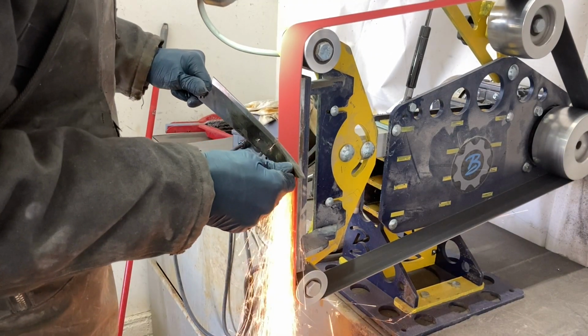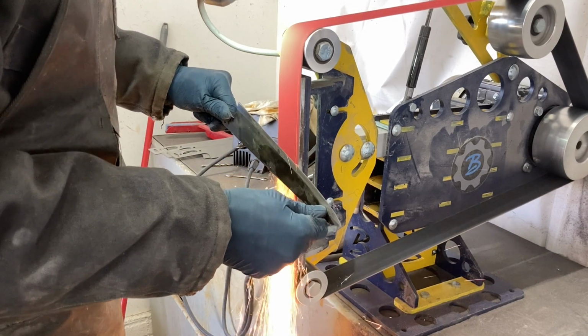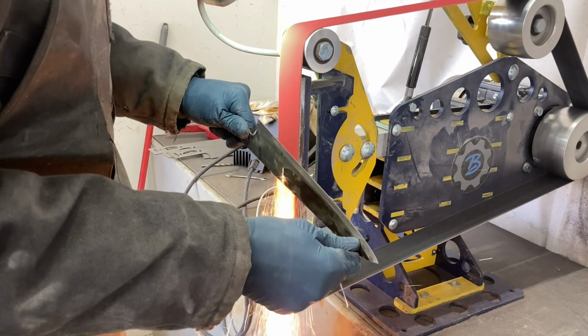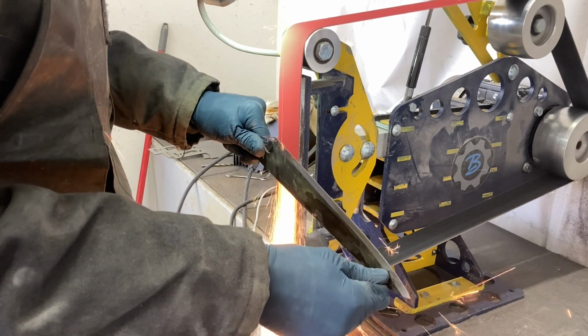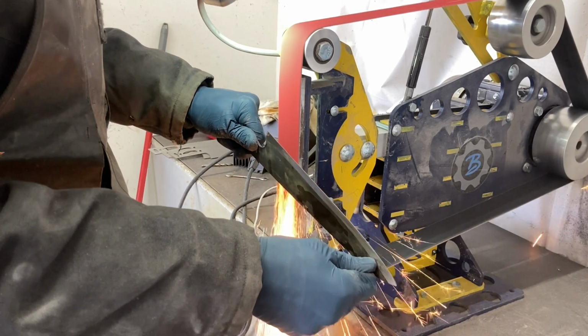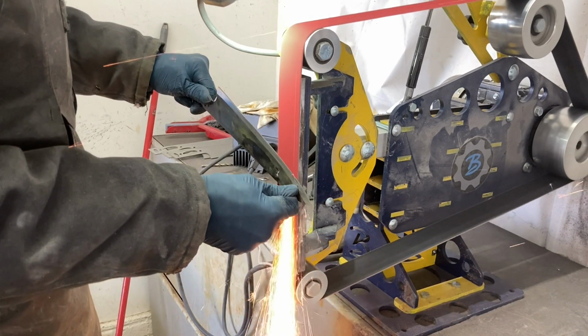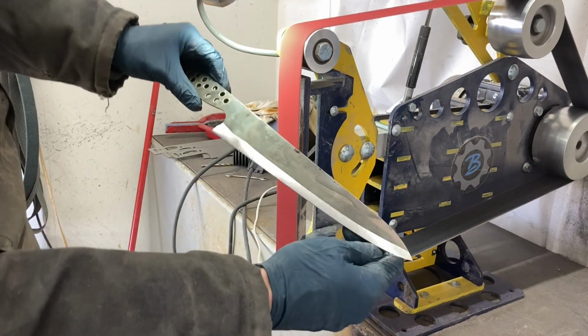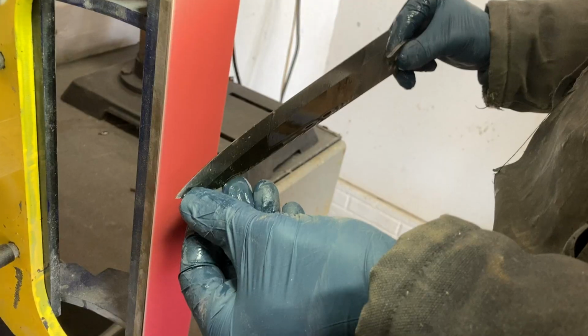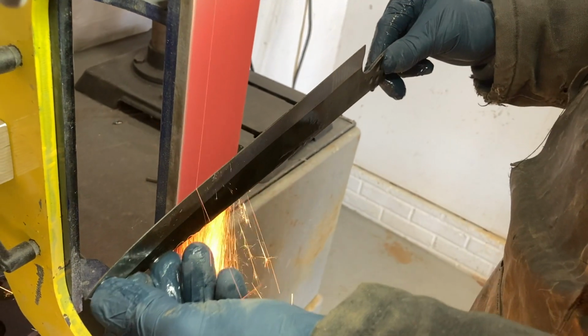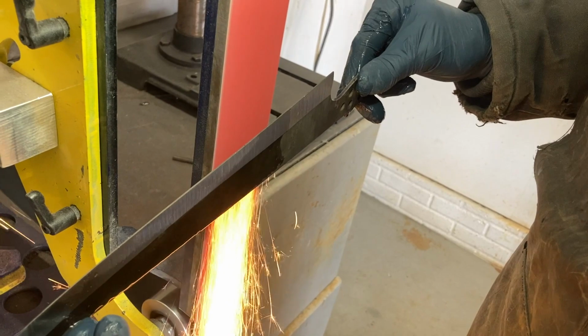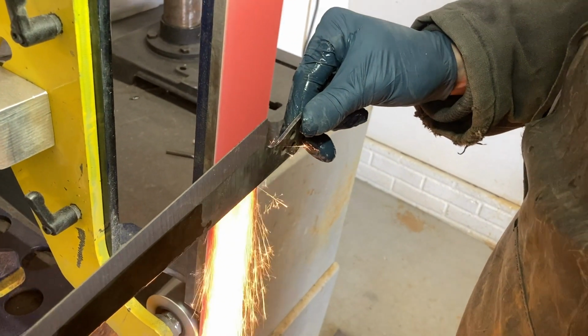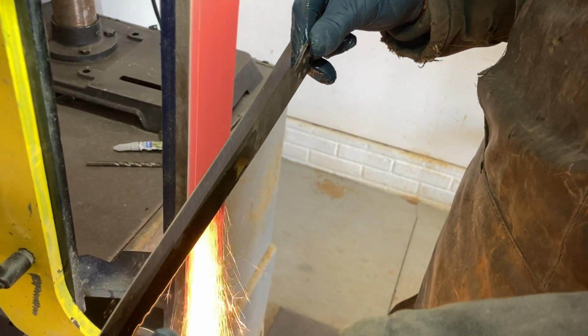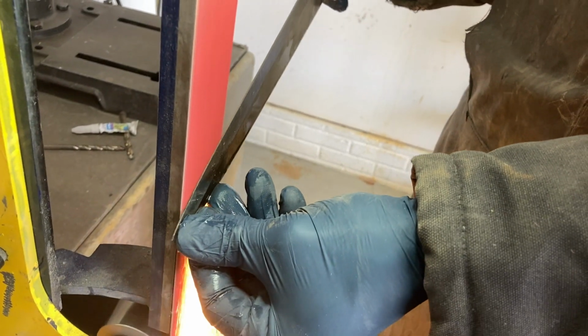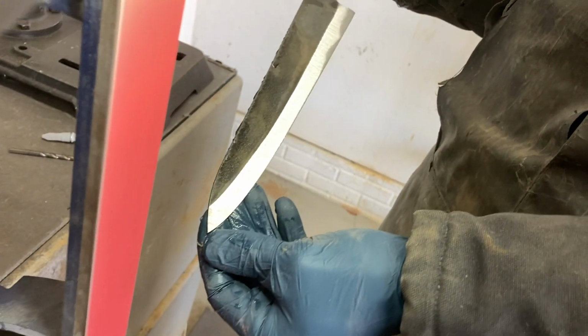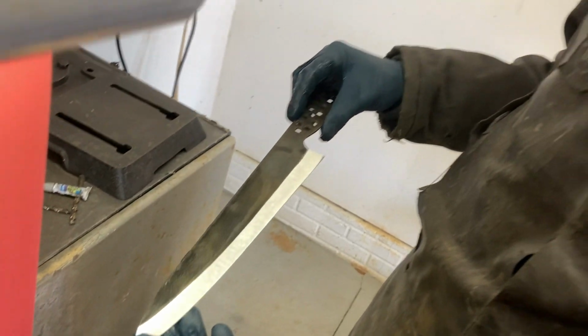When I'm starting the grind, I always make sure that I cut in the rough 45-degree bevels to give me something to grind to, and then I make sure that I periodically dip the knife into the water bucket that I have below my grinder, and that enables me to keep the blade nice and cool so that I prevent ruining the temper. Because if you heat the knife up too much and heat it past the tempering point that you heat treated the knife to, then the edge can start to become soft and it'll no longer hold a sharp edge as long.